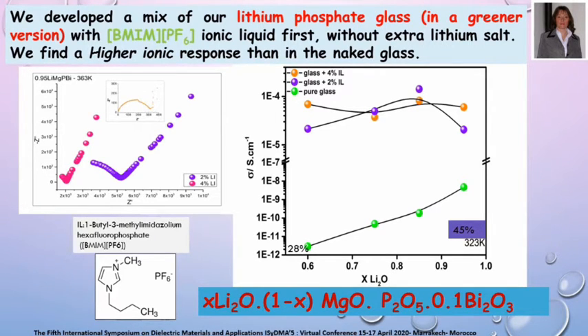First, we studied the electrical response without the incorporation of extra lithium salt, considering that our glass already contained mobile lithium ions. The result, as we can see in this plot, is that the conductivity is higher than the naked glass, but almost independent of the composition of the glass as substrate. Therefore, we are testing the electrical response of only the ions that can release from the glass and move along the grain boundaries.